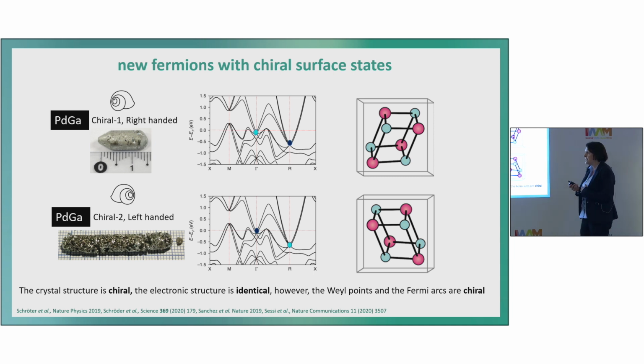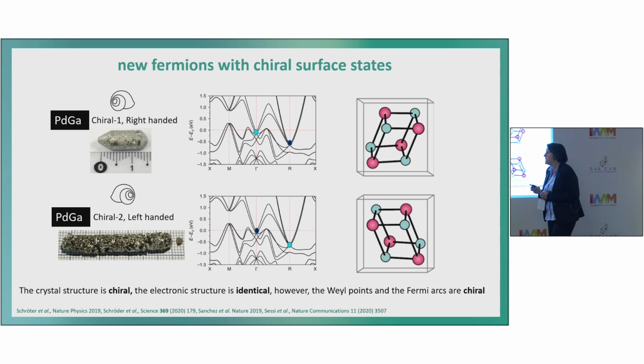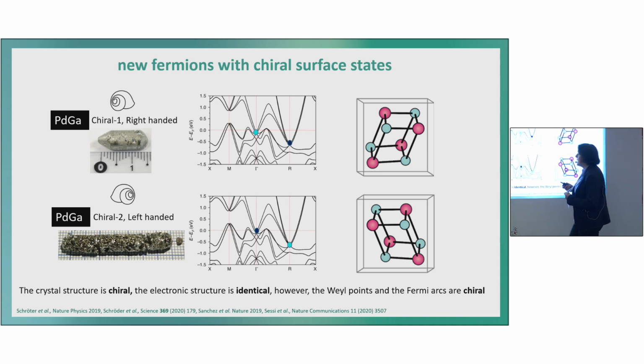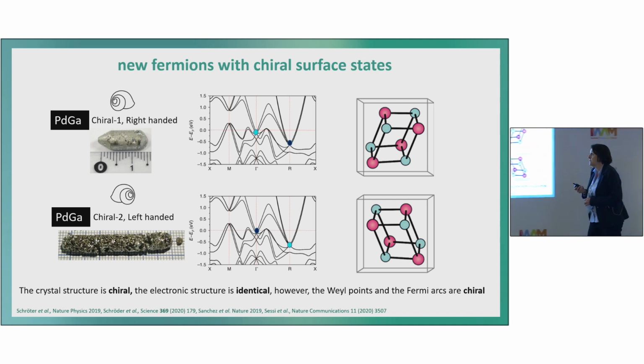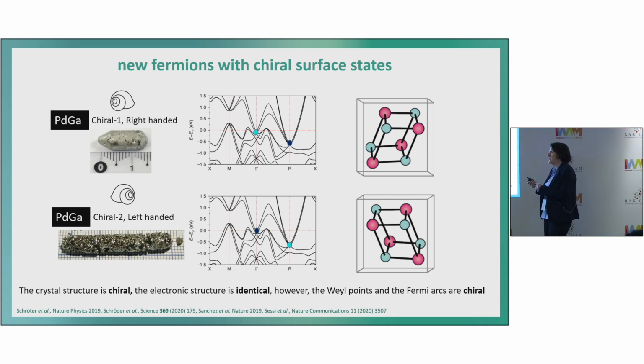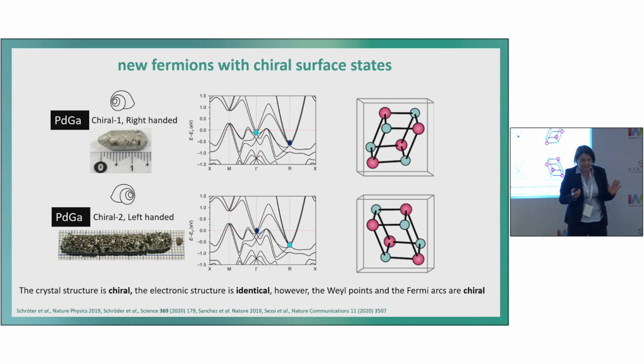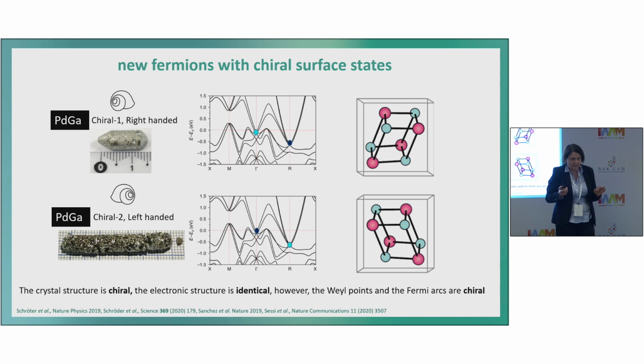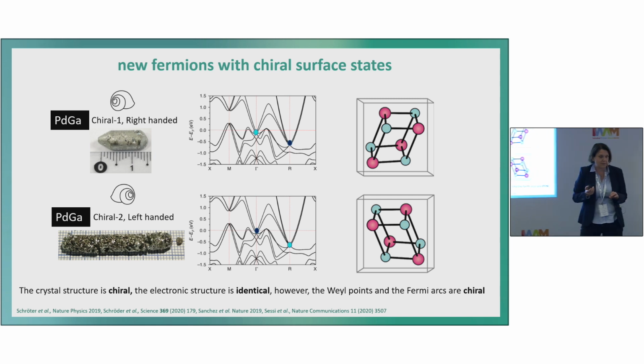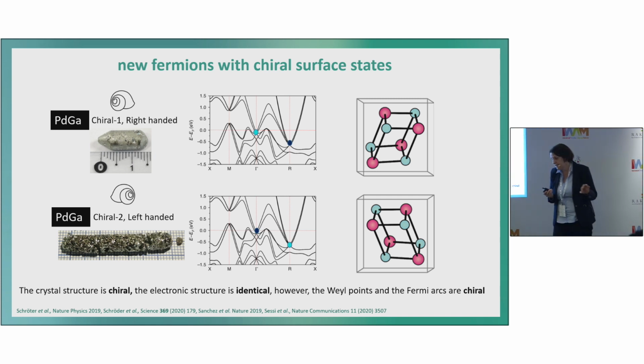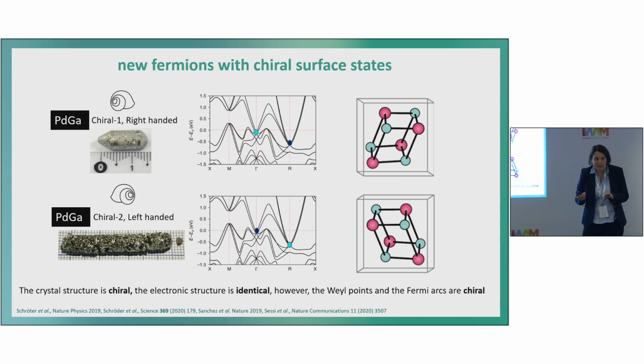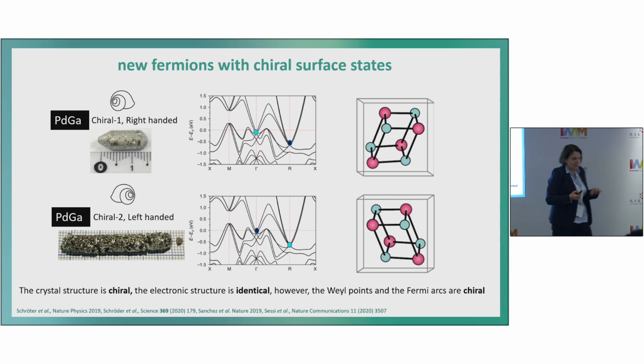Okay, so luckily we were able to grow from one crystal even two chiralities. This is palladium-gallium, where we could have the right- and the left-handed. I have to honestly say it's more or less still statistics. You can use a seed crystal to get especially one chirality, but it's still a debate even in our institute whether it's possible or not.